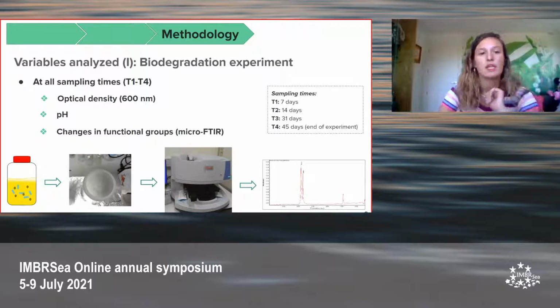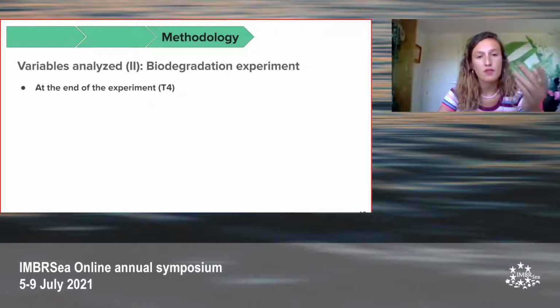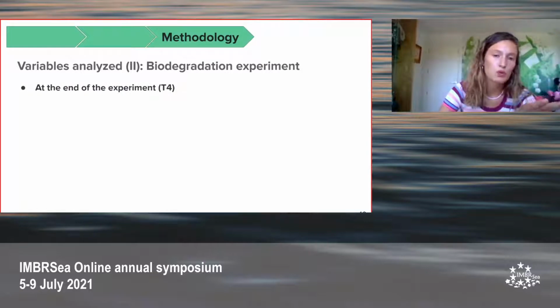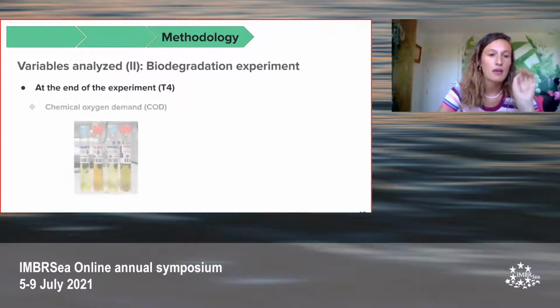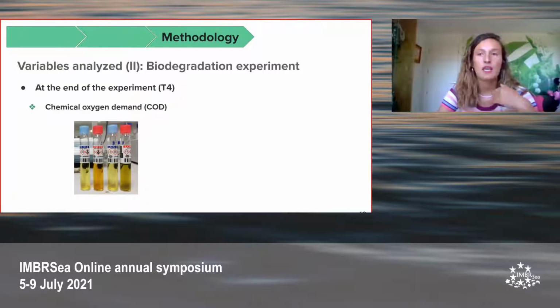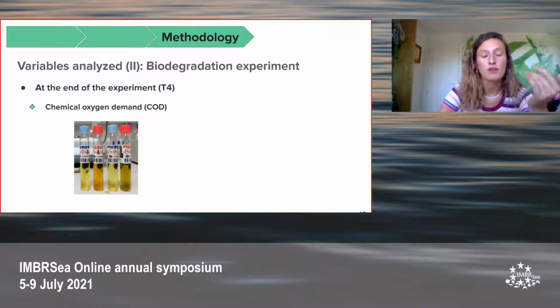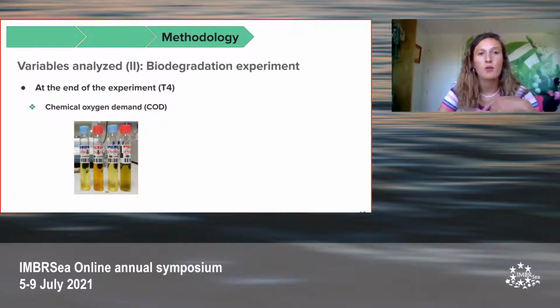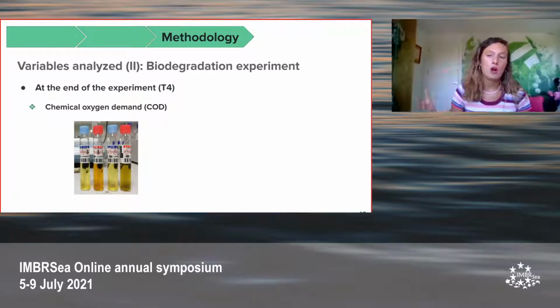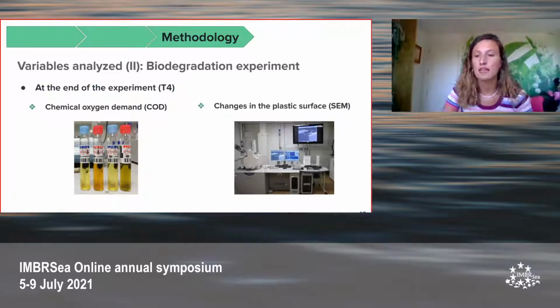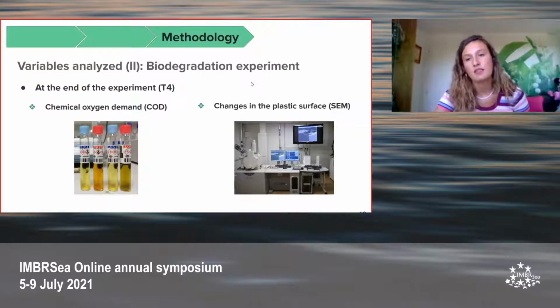time and treatment. Also, at the end of the experiment, we measured two other variables: the chemical oxygen demand, which indicates the amount of oxygen that is necessary to oxidize the microplastic particle. So the lower the value, the more biodegraded the particle will be, and vice versa. Also, we analyzed through scanning electron microscopy the changes in the plastic surface of each polymer.